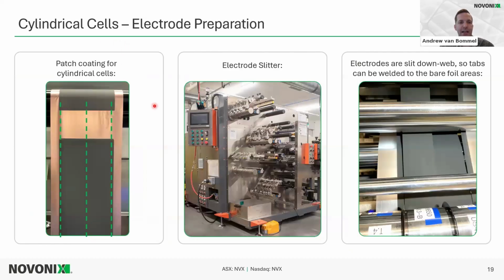So to prepare the electrodes for cylindrical cells, we don't use a continuous coating, we use a patch coating. In a patch coating, there's an area of intermittent coating, or skip coating, an area that has no electrode coating, shown here. After that coating is finished, the electrodes can be slit to a size, a height, that will fit as the jelly roll into the can. The reason for the patch coating is that area will be required for the tab welding.